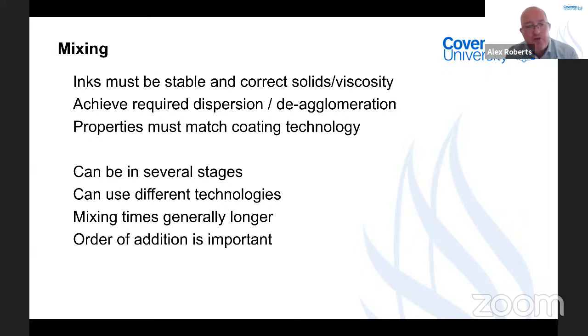I refer to it as a very necessary evil. You cannot make a lot of these electrodes without a conductive additive, which is normally a carbon black, but it can be challenging to work with, particularly in terms of its dispersion. Mixing times, as you go to larger scales, are generally longer than you would expect. I very rarely do any mixing that takes less than 3 or 4 hours. And it's not uncommon for the mixing to take a whole day or longer. And you can find that as you put more and more complex additives into your system, the order of addition of your components can be very, very important.